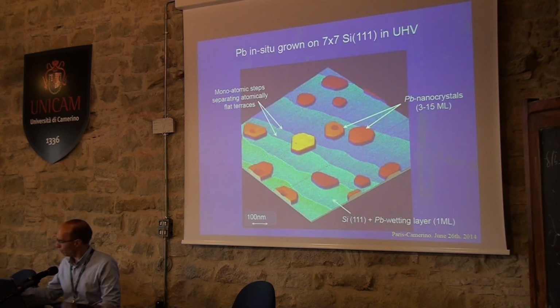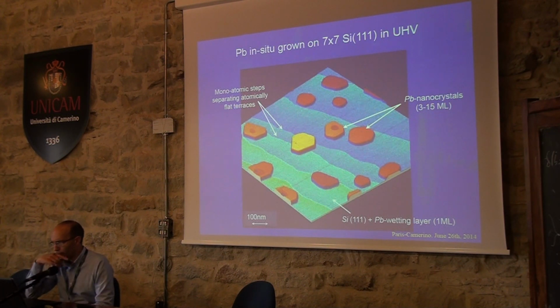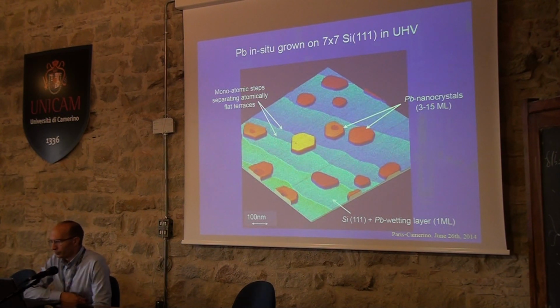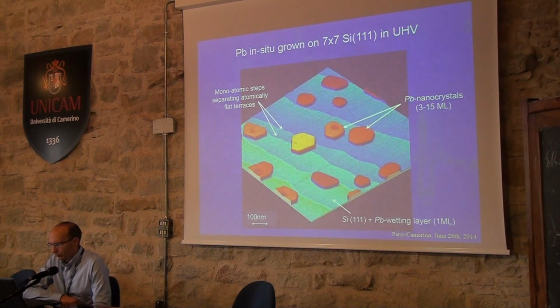Next slide, please. So when you put lead on clean silicon, which is 7 by 7 reconstructed, you get this specific growth, which is called Stranski-Krastanov growth. Because of lattice mismatch, the lead islands grow. You see them in red, and also you have the silicon surface, which appears here as bright blue, which is covered by a single atomic layer, which is called the wetting layer of lead. And this wetting layer may be of very different structural compositions.